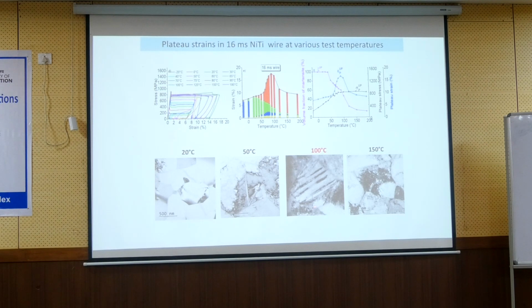And inside the microstructure, there is lots of deformation bands like this. So this is in here. And when you go even higher temperature, like 200, lots of dislocations, but not many deformation bands. And